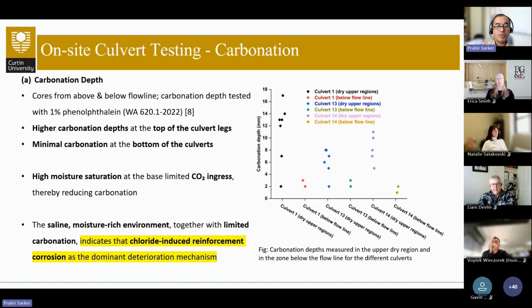had high moisture saturation at the base, which limited carbon dioxide ingress. So looking at the results, culvert legs above the flow line had high carbonation, and below the flow line had low carbonation.